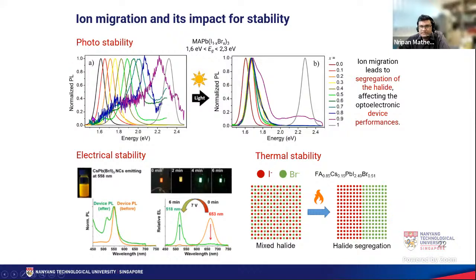For example, if you take, in this case, let's say 7 or 8 different types of halide perovskites of different composition, and you shine light on them for a long time, you can see that the compositions have transformed into a few compositions. If you make a light emitting diode out of these systems, after a long time heating, the color of these systems changes. And the color changing is synonymous with the halogen segregating within it.